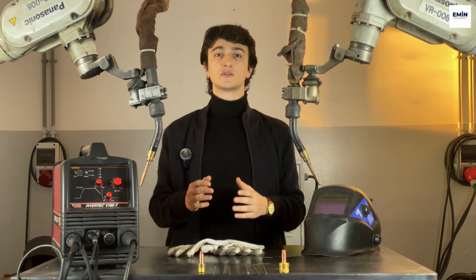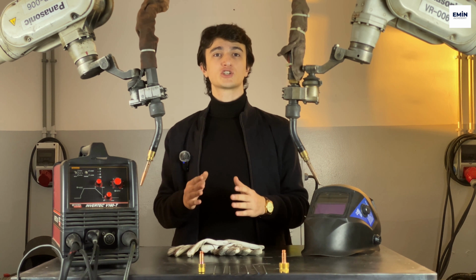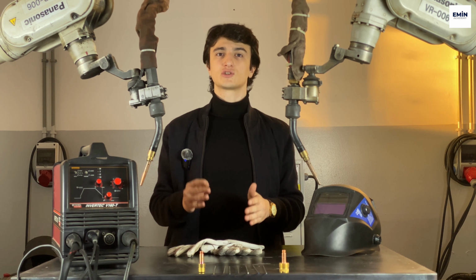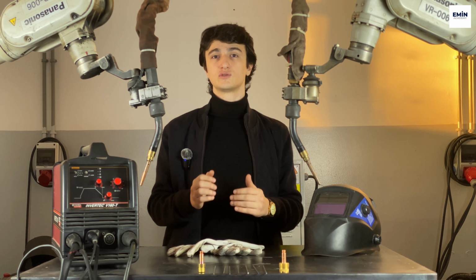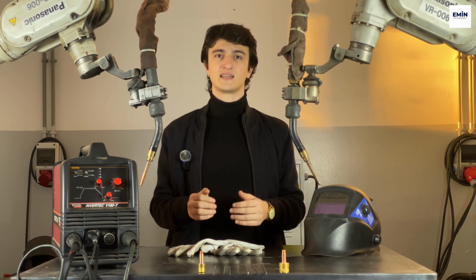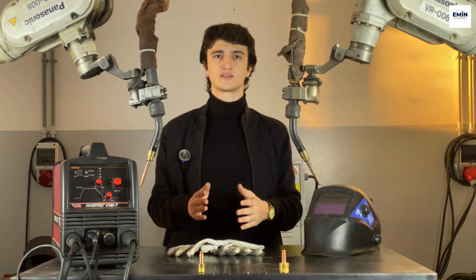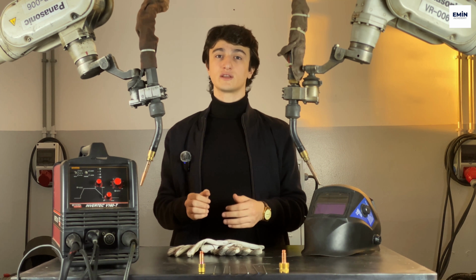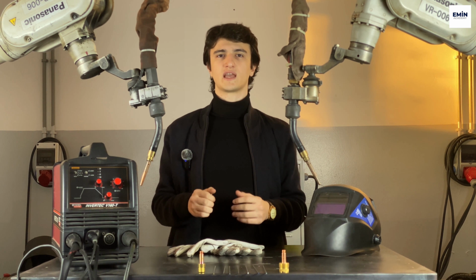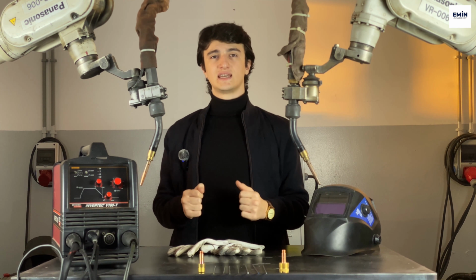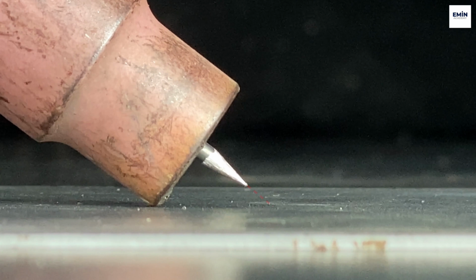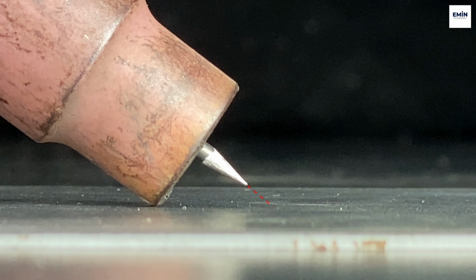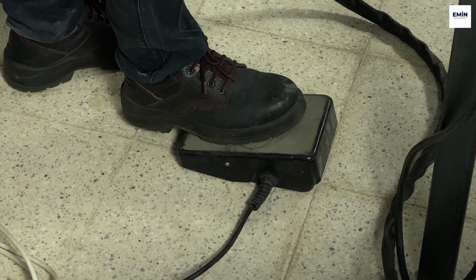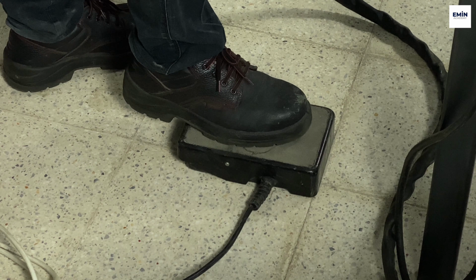Cleaning with acetone before welding and using a wire brush specific to stainless steel is essential. Wire brushes and stones used on carbon steel contaminate stainless steel and cause rusting later on. If you see rust after welding, the reason is 90% contamination. Stainless steel retains heat. That's why the arc distance is kept short. The torch is advanced in a steady manner. The amperage is constantly adjusted with the foot pedal.